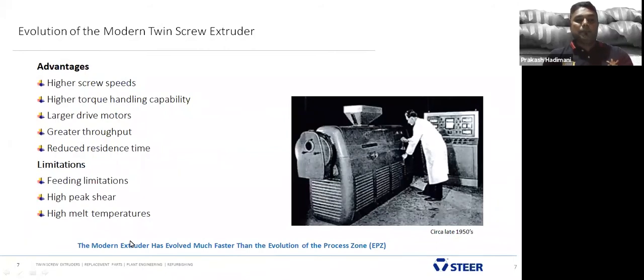See, the 20th century has twin screw, high screw speed, it's already built. Many extruders had 1200 RPM and higher torque handling capability, larger drive motor, and also greater throughput and lower residence time. What are the limitations? Feed limitation and high peak shear, higher melt temperature.